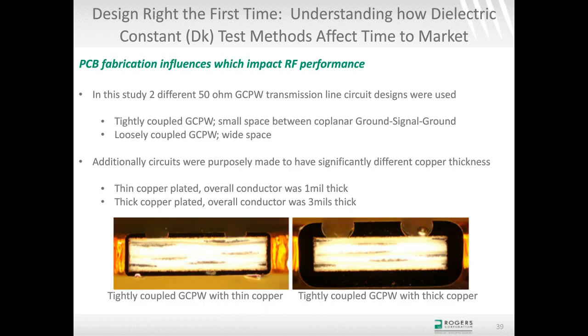For the grounded coplanar waveguides, there were really two different designs: tightly coupled, meaning the space between the signal and the neighboring grounds is small, and loosely coupled. And then the copper plating thickness on the final circuits, the thin plated circuits, was 1 mil thick copper, total copper thickness, and the thick copper plated circuits had 3 mils. So there's a pretty big difference in copper plating thickness there.